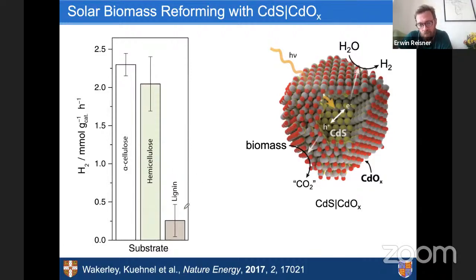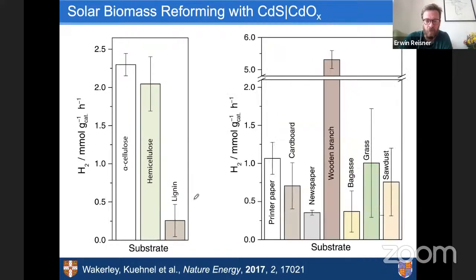The lignin, much less so, simply because the alkaline solutions very nicely pre-treat the cellulose, depolymerizing it, whereas the lignin is much tougher to work with. So the alkaline conditions are not just a nice protection layer for the cadmium sulfide, they also help us pre-treat our cellulose. And this works for real world samples as well. The students got quite excited collecting grass from different colleges, collecting printer paper from waste bins, cardboard, et cetera. So you can see all sorts of lignocellulose or comparable materials being converted to hydrogen.